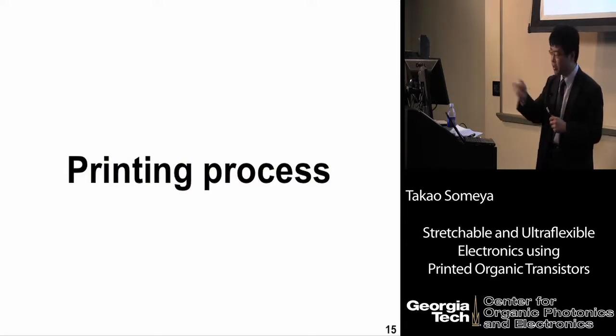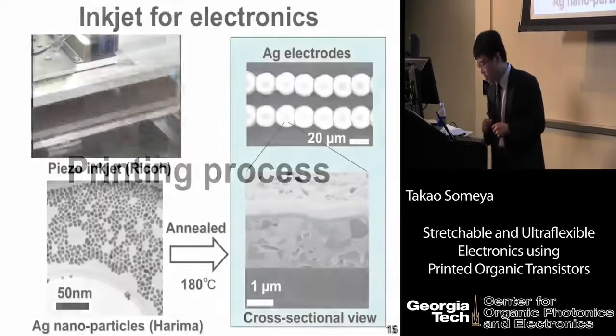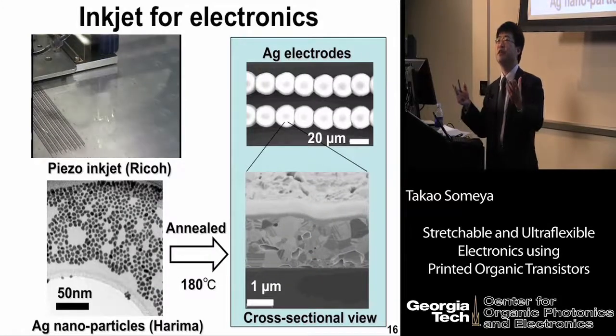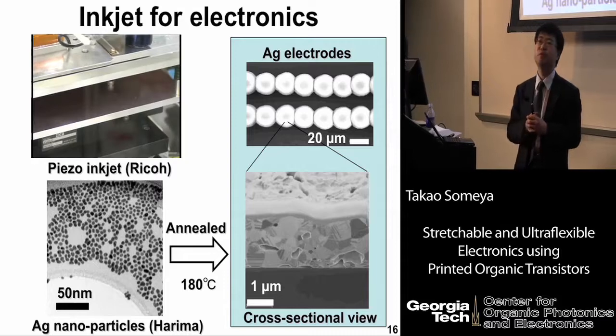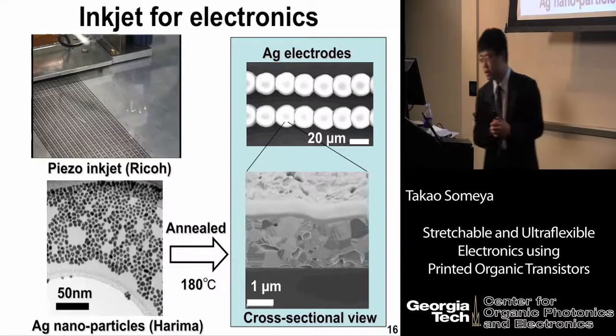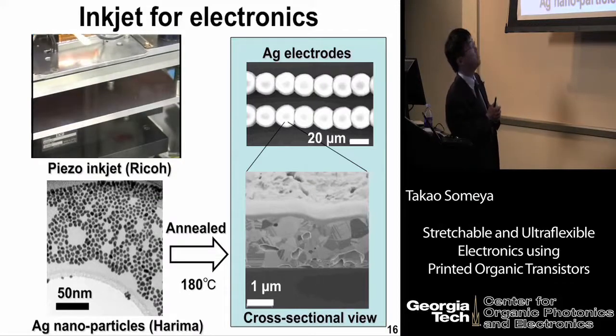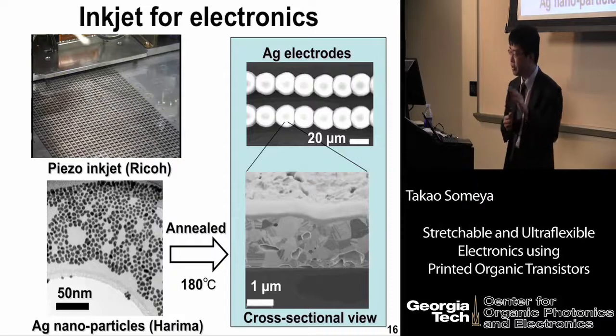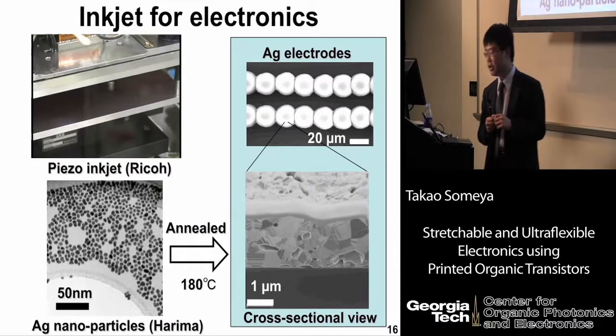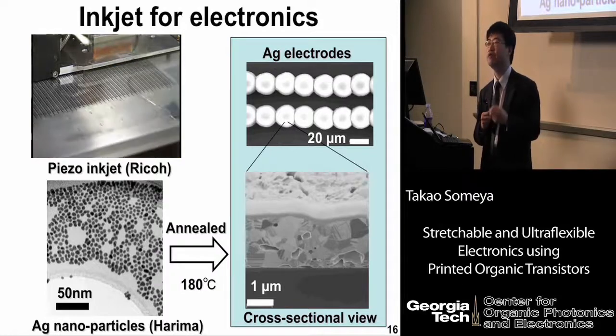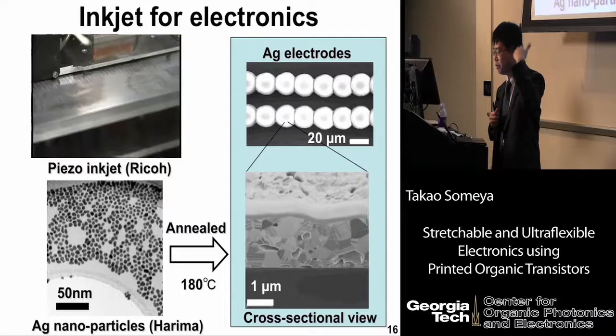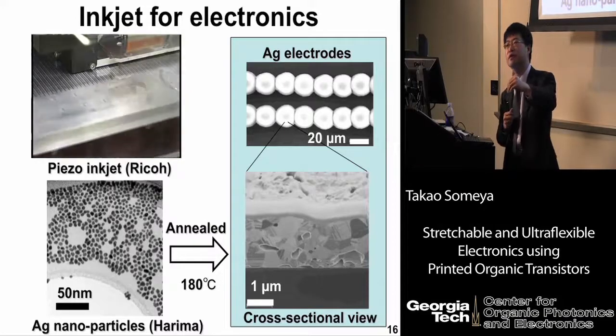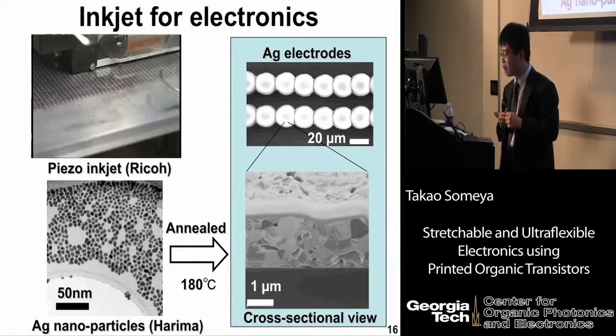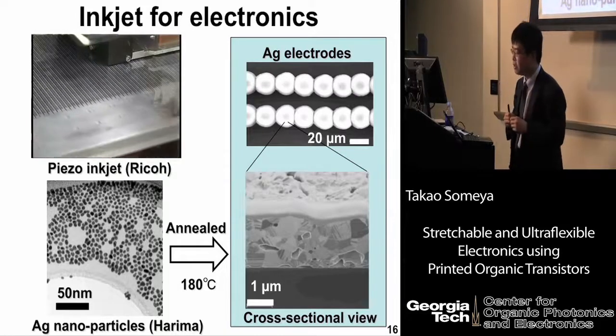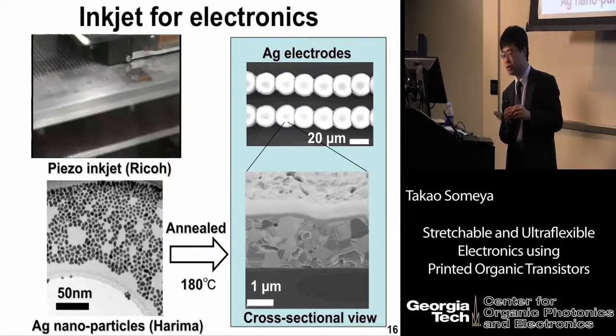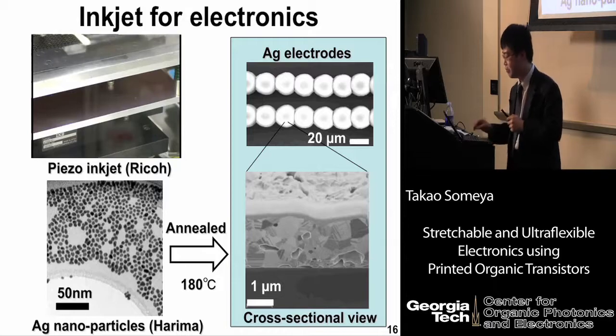So then I would like to start talking about the printing process. In order to make the large area prototype, printing processes play a very important role. This movie shows you the direct writing of silver electrode using silver nanoparticles. Here, the silver nanoparticle comprises a 2 or 3 nanometer dot, and that will be delivered onto a surface of plastic film. After the direct writing of silver electrode on plastic film, the substrate was annealed at 180 degrees Celsius or so to get the dense silver film.